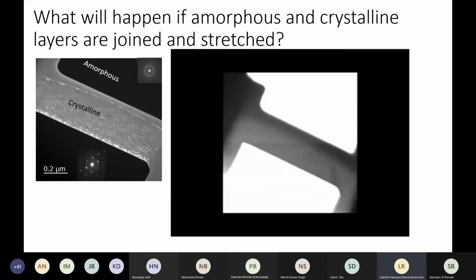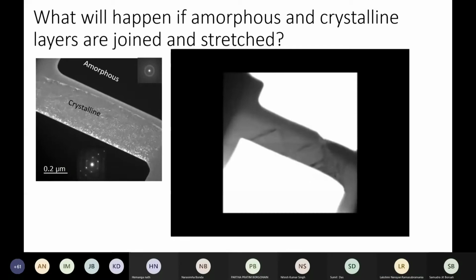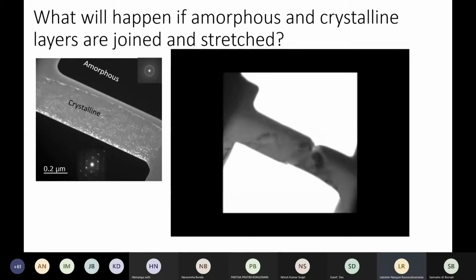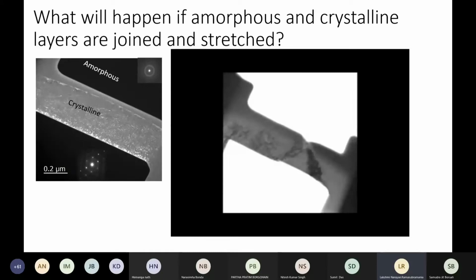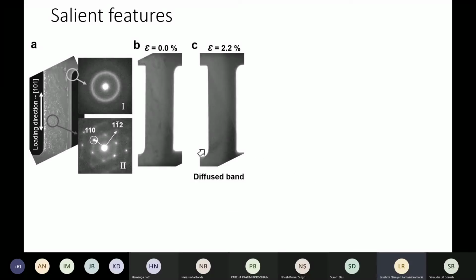If you observe, nothing happens for some time, and then you observe the formation of very thick bands, and these thick bands extend throughout the crystal. And finally, the amorphous phase starts deforming a bit, and you see that the crystal will fracture. So at this moment, your uniform elongation stops when the amorphous material has yielded. And let us look at the salient features one by one.